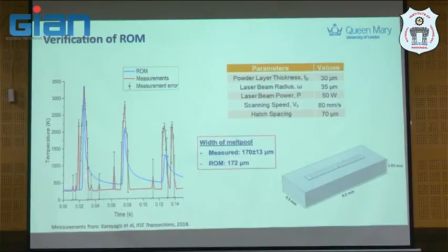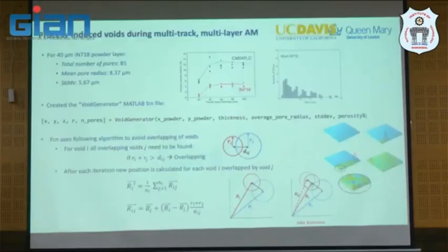So this is a temperature field that we use from this paper here. And you will see the prediction and the measurement of the melt pool don't make a big difference. So that means the model is reliable at some level here. But the next step for us, you will see the model doesn't take into account the defect which is formed during the process yet.